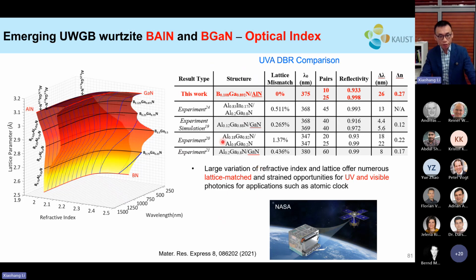So another interesting thing for optical devices is refractive index. In the past, when you wanted to realize good epitaxial DBR layers, you always had to balance the lattice and strain, right? Because mostly when you have a heterojunction for the DBR epitaxially, you always have some lattice mismatch, especially when you want to increase the delta n between the two layers. The higher the delta n, the better the DBR, and the fewer pairs you need.